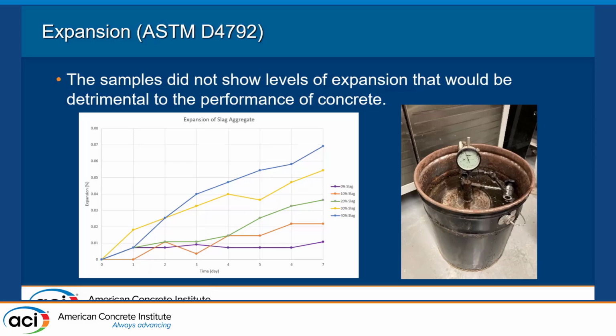And on the graph on the left, you can see the expansion over the duration of the test for the 5 mixes. And as expected, we saw the aggregate expand as the test went on, more so as we increased the replacement level of the slag. But as you can see, our expansion over 7 days did not go above 0.07%. And according to the majority of literature, the limit on aggregate expansion in concrete ranges from 0.08% to 0.1%. So this falls even at the replacement level of 40% below this threshold, meaning it could be a viable supplementary coarse aggregate.